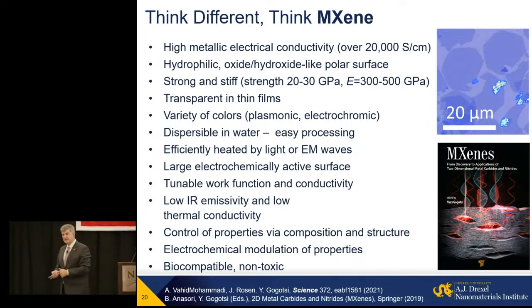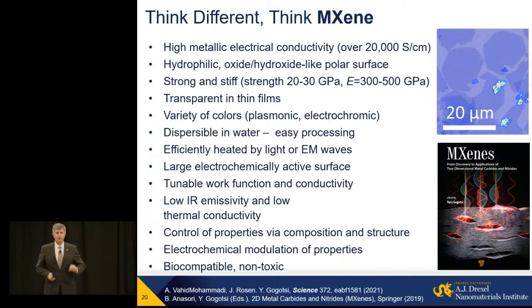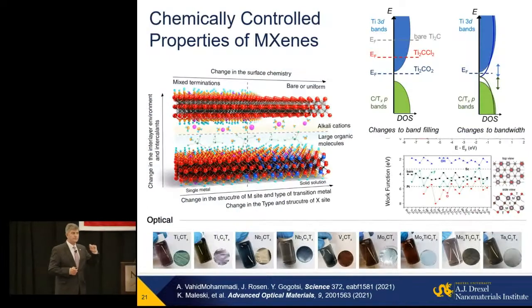So you get a material that is metallically conducting, very strong, processable from pure water, the cheapest and safest solvent. And they come, as you have seen, in a variety of colors, with very diverse plasmonic properties, very strong interaction with electromagnetic radiation from X-rays to microwaves and radio waves. Plus, all these properties are highly tunable. Plus, biocompatible and non-toxic. At least I'm talking about titanium carbide, niobium carbide, tantalum carbide, a number of materials. Of course, I cannot generalize in that particular case. So that's very important. But the most important thing is that they're tunable.